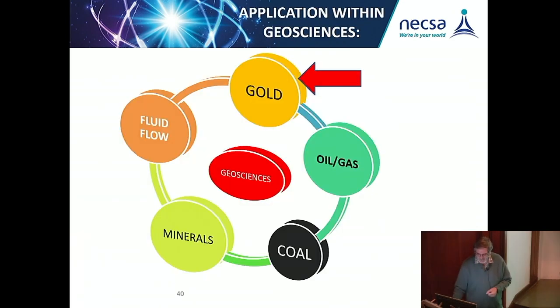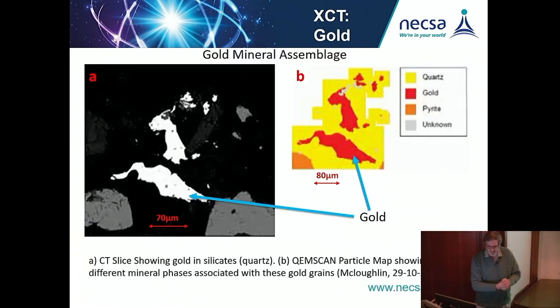What about gold? Here I must say that once you do X-ray and neutron tomography, the signal that you get doesn't show that this is gold, this is pyrite, this is hydrogen, whatever. So one has to benchmark your neutron or X-ray CT signal with another technique, either SEM work, X-ray diffraction or QEM scan work. So here you can see how a slice through an X-ray CT represents also a QEM scan map of gold in this regard. So it works nicely. Once you benchmark it with respect to another system, then on a certain level, because this is a slice, you can extend it into the total volume of that sample to get the volumetric detail.